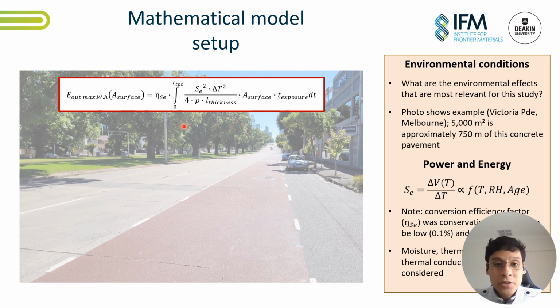We can estimate the energy output through this mathematical model, which depends on the Seebeck coefficient, which has a squared effect, and the electrical resistivity. So, as I said earlier, we have to keep an eye on the electrical resistivity. The lower, the better, and the higher the Seebeck coefficient, the better. But it's not that easy. The perfect scenario is that we increase the Seebeck coefficient and reduce the electrical resistivity. Those two have a coupling effect. As I improve one, the other gets worse. Getting the perfect balance and how to enhance both of them for our purpose is part of the study, and many people have been researching that lately.